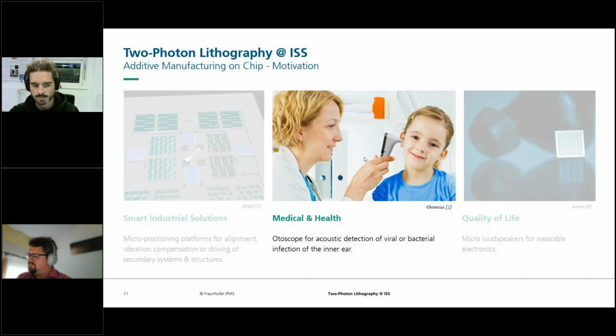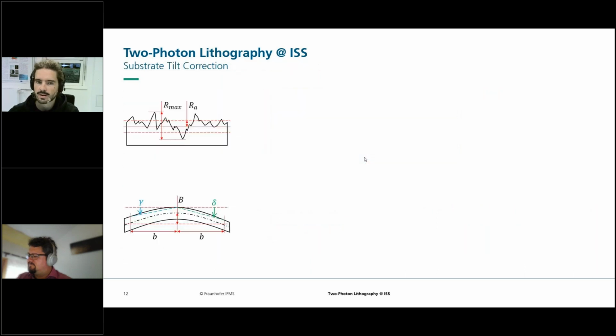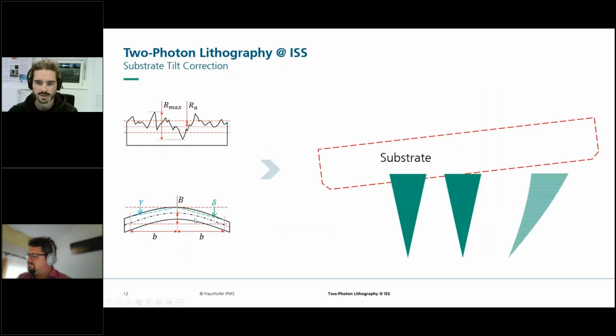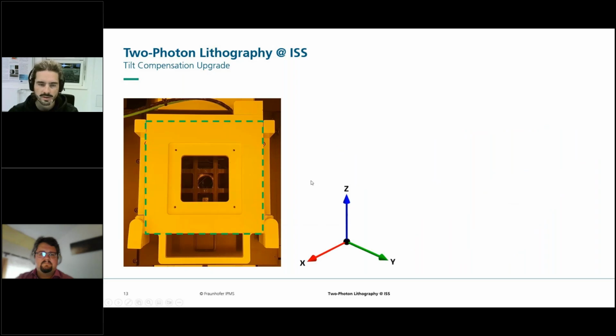First of all, we have to put the chip inside the system. If there's roughness or wafer bow, for example, a substrate can be tilted towards the optical path. If you print on it, you will end up with structures either being inside the substrates, partially disconnected, or just completely disconnected. To fix that, I improved the system by giving it a tilt compensation upgrade. Here we have a look inside the system from the top, looking at the optical path.